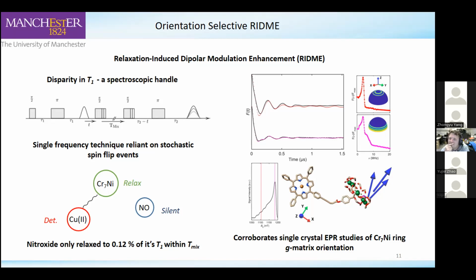Well, I guess it's mainly based on the freezing point of the solvent mix that you use. But we did do DEER between the copper and the nitroxide at 50 Kelvin. And it was evident from that alone that there was a little bit more flexibility in the length of the linker. The interactions between the copper and the nitroxide were less. We have these really, really well-defined higher frequency components to the trace when we're looking at the XY position of the copper.